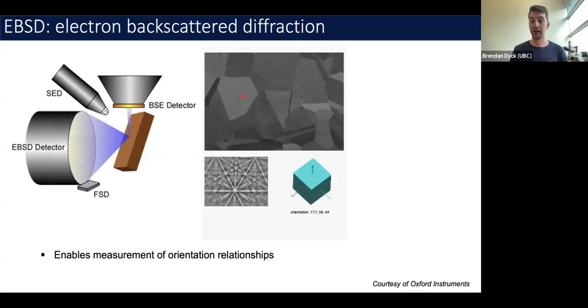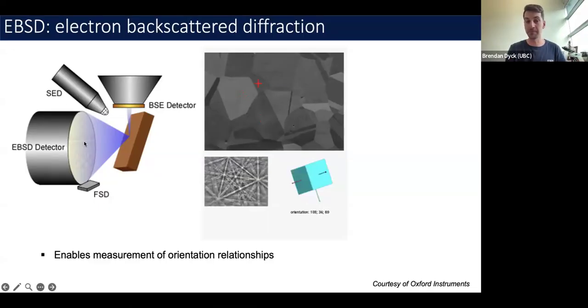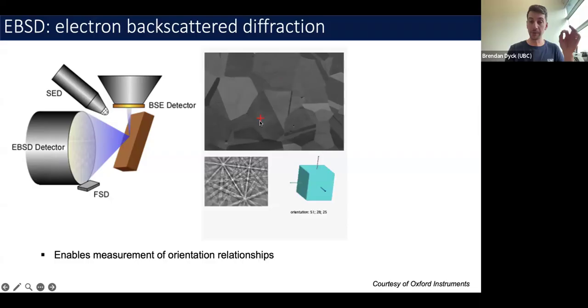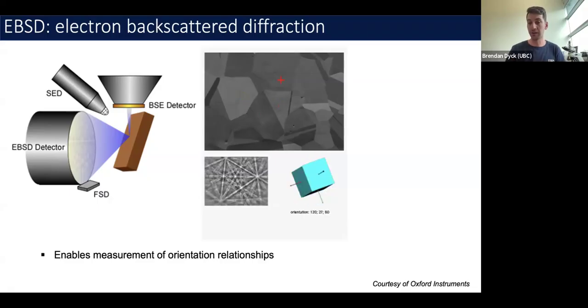So EBSD is an SEM-based technique where we hold our sample at a very high angle to the primary beam, usually 70 degrees, and then we look at the near surface diffraction or forescattering of electrons. Where they interact with the crystalline lattice, they're either able to pass through or they get blocked by the atoms. And so that develops these Kikuchi patterns, the array of electrons that then interact with a phosphor screen. They light up, and we just snap a picture of that with a camera. So as we move around, this is an example of steel, so a cubic metal. As we move around to different grain locations and we move our beam, we're getting a different pattern. And then the program or the detector in your system will index and determine what the structure of that mineral is, as well as, importantly, the orientation of that mineral. So it enables measurements of orientation relationships down to sub-degree accuracy.